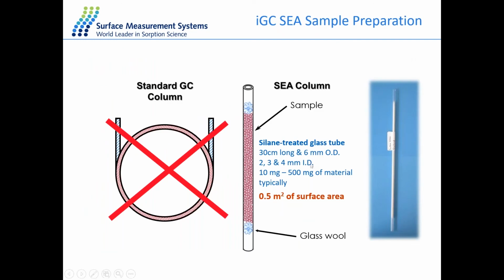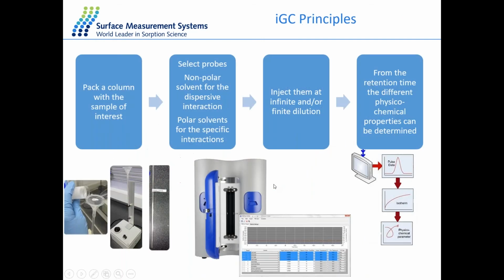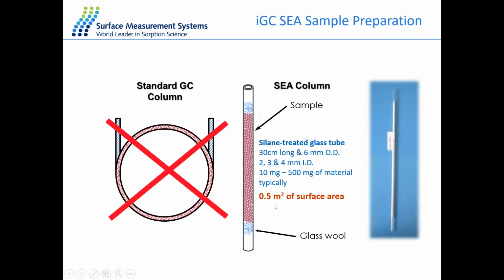To prepare a sample for IGC-SEA, it's very different from the standard GC column. It's much more straightforward. So what we have is some silanized glass columns. What we effectively do is plug in some silanized glass wool. And in this case, we then funnel in our sample of interest and close off with some more silanized glass wool. So in this case, we don't have any of our material going into the lines of the system.